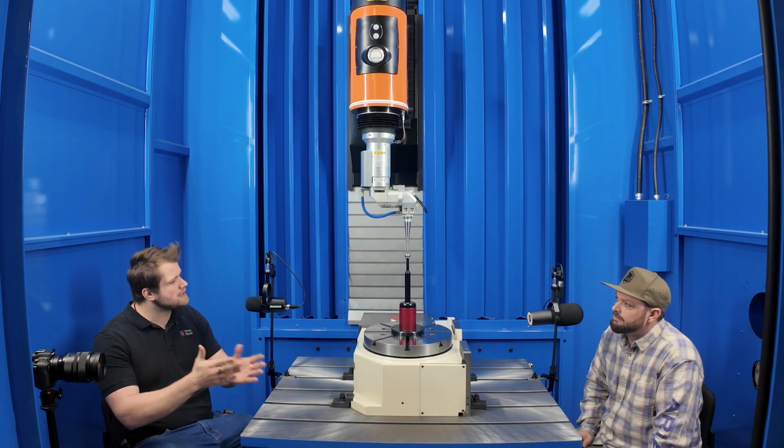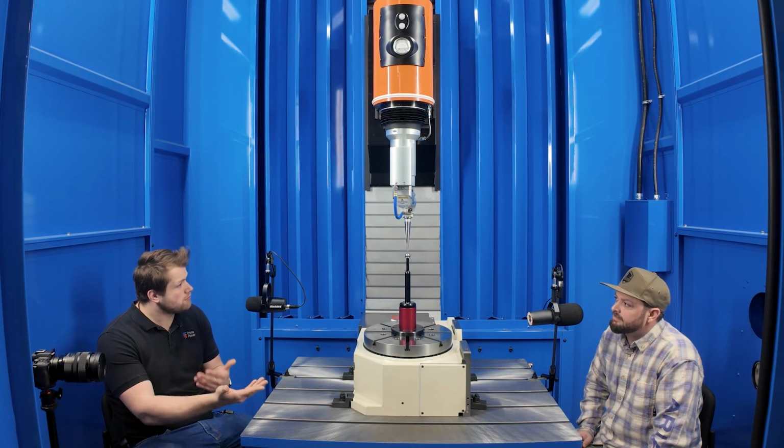When you fire a hole with a laser, what happens is a lot of the initial force, when you hit something with a laser, it wants to bounce back at you because there's no hole drilled through it yet. And so what happens is your hole looks a little bit like a triangle. It's very tapered. The entry side where the laser hits the surface, that hole may be double the size of the exit side. And so, we talked a little bit about if you do 2 shots per hole, 3 shots per hole, what that does is it straightens out that hole, makes it look like a hole, just like a regular hole. Parallel lines.